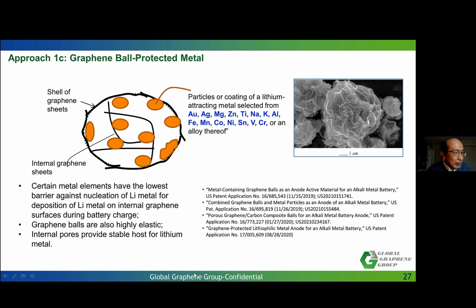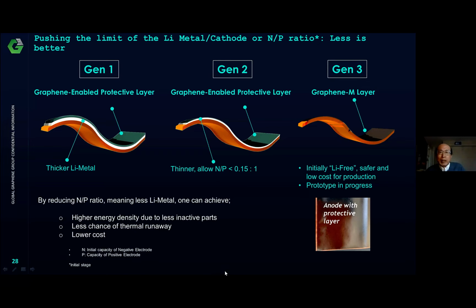All right. And because of that, we have been continuing to improve our graphene-enabled lithium metal battery. We'd like to reduce the amount of lithium metal. If you are able to reduce it down to essentially zero, then you have the so-called anodeless lithium metal battery that will reduce the cost and also the volume and the weight of the entire battery, and thereby increase the energy density of the battery.